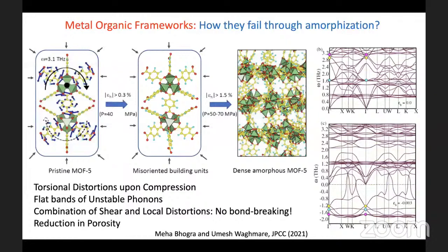So we have used here computer simulations based on first principles density functional theory to show that, as seen in the first picture here on the left, there are torsional modes of various molecular moieties which become unstable at very tiny pressures. And this is the phonon dispersion of the starting MOF at zero pressure. And this is at a very tiny strain.